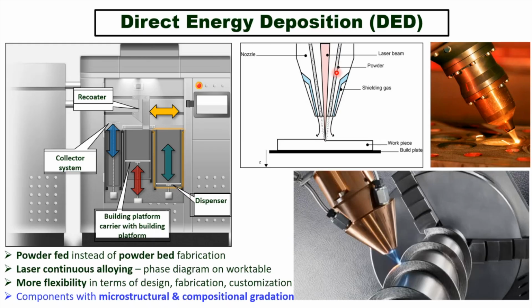Coaxially, you have feeder channels through which you feed powders, and you shield them with certain shielding gases to prevent undue oxidation. The powder interacts with the incoming laser beam in flight, gets molten, and then gets deposited onto the surface. This is how you develop a layer.